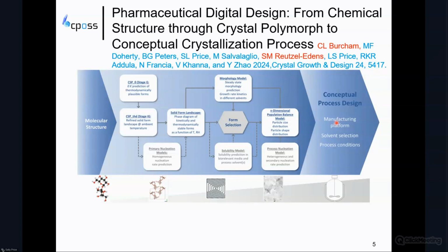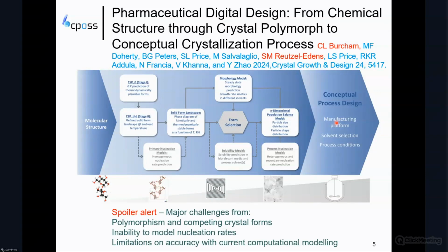Spoiler alert, we tried this on succinic acid and olanzapine and could show that there are still major challenges for this conceptually fine idea from the degree of polymorphism and the competing crystal forms, and our inability to model the nucleation rates you need. There are also quite a lot of limitations on the accuracy with current computational model, because so many of the features are exponential in the energy differences.